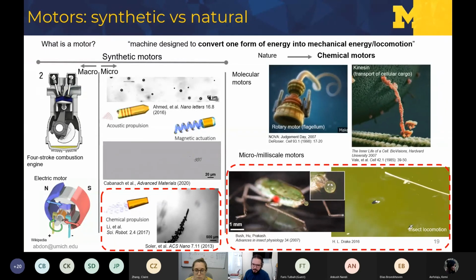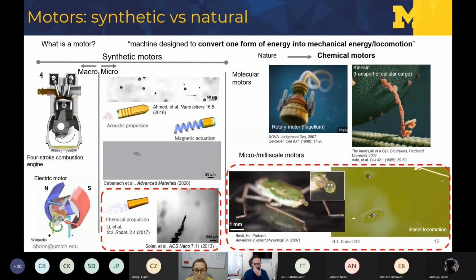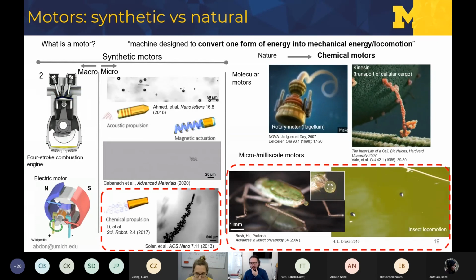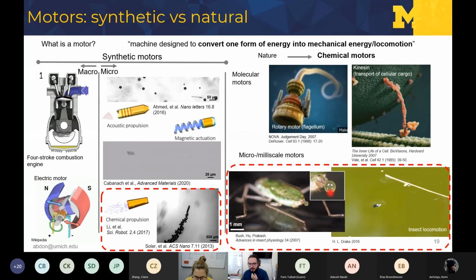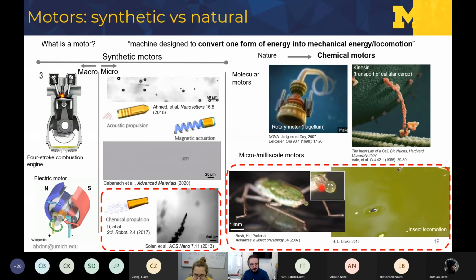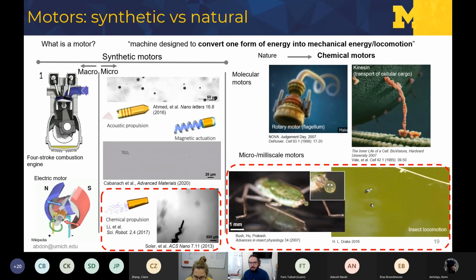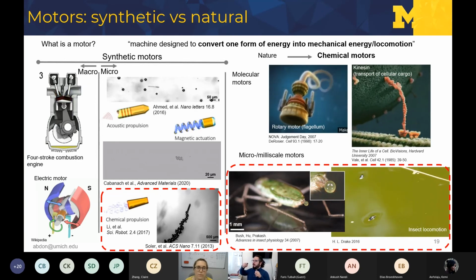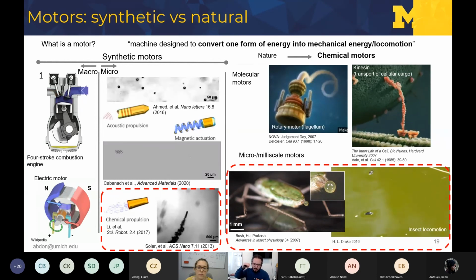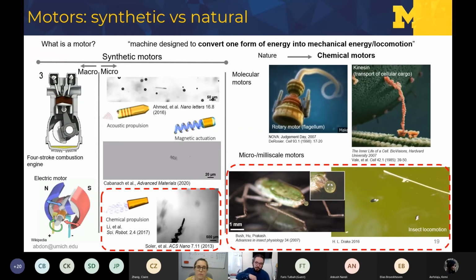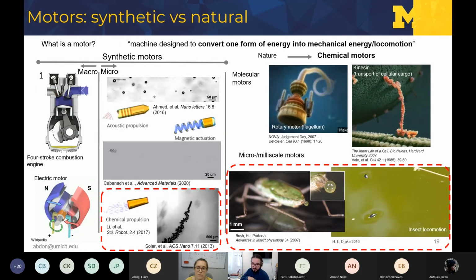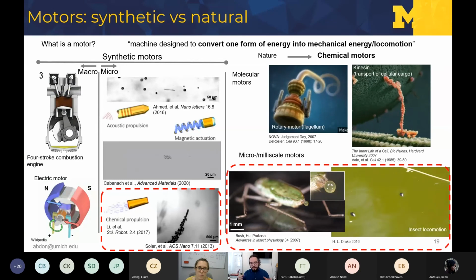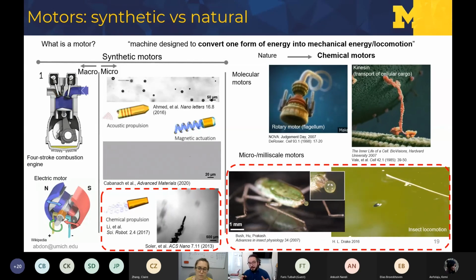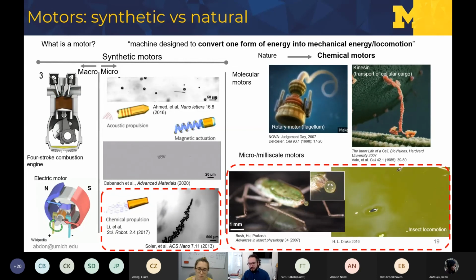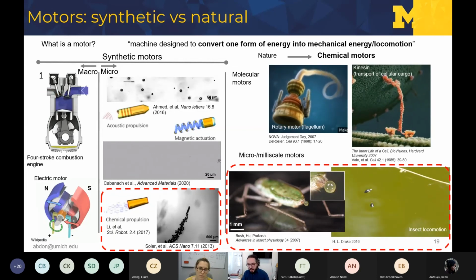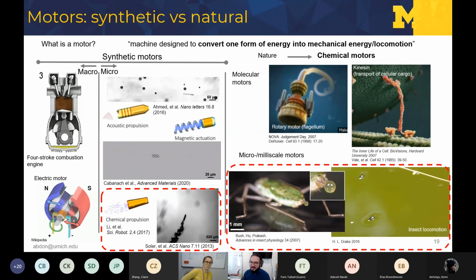Specifically, this little guy over here comes from a family of insects, right? Mesovelia and Microvelia, that secrete this surfactant, and they float on the surface of water. But when they need to run away from predators, they dip it in the water, and because it's a surfactant with very low surface tension, when it touches the water, it locally decreases the surface tension, generates this very anisotropic surface tension gradient around the insect, which generates Marangoni propulsion forces, and they go really fast with it, so they can escape from the predators.